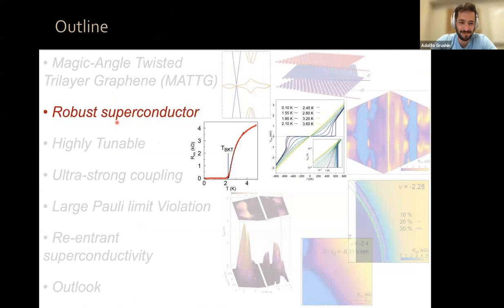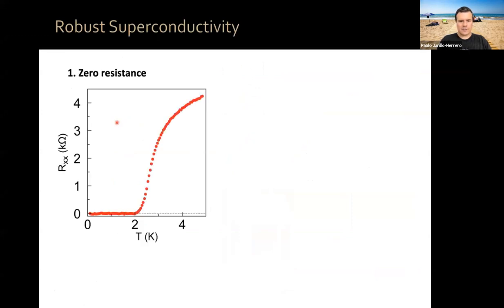Good, thanks. All right, so let me show you that we have a robust superconductor. So again, what do we want to see? We want to see first zero resistance. And indeed, if you measure the resistivity of magic angle trilayer graphene as a function of temperature, you see this drop to zero. You can fit this with the Halperin-Nelson formula and extract a BKT, Berezinskii-Kosterlitz-Thouless, transition temperature, which in this case is about 2.3 Kelvin.